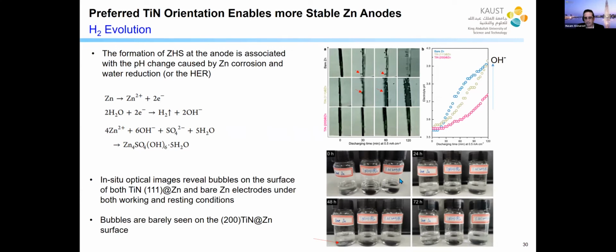You can also see this visually on the electrode itself. This is after cycling for 48 hours. You see the bubbles here, but you don't see them in here for the (200) TiN@Zn. So the story is very clear. This layer suppresses this second phase formation. And we therefore made some batteries to compare.